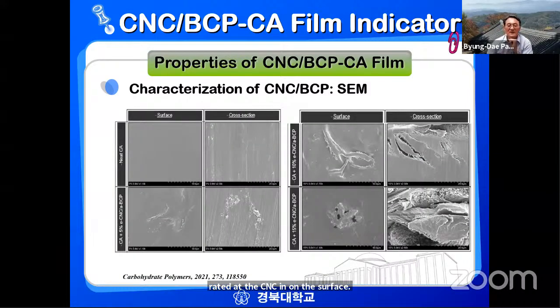So we also looked at the film morphology with the SEM. The controls are very nice films, and the surface and cross section. The 5% composite material, CNC and activated BCP, is a little bit rough, and the 10% and 15% are a little bit rough as well. Some materials aggregated in the matrix. This kind of problem always happens in other polymers as well.